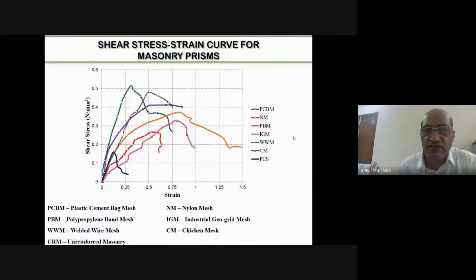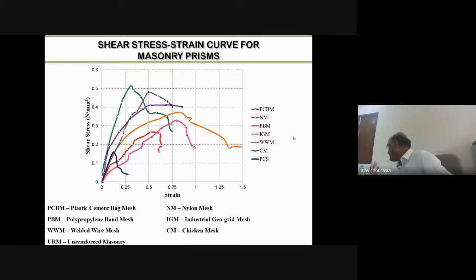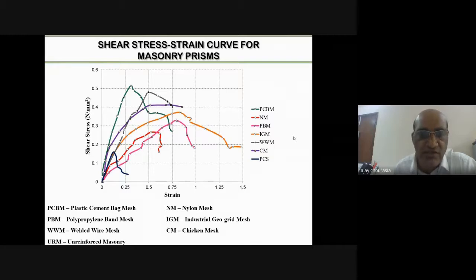And again, the results were plotted in terms of shear stress and strain, which again shows substantial enhancement in the shear strength in case of plastic cement bags, and when it was jacketed using the welded wire mesh. So that is building confidence that we can phenomenally increase the shear strength, compressive strength, and tensile strength upon implementing all these different options when compared with the control specimen of the unreinforced masonry panel.